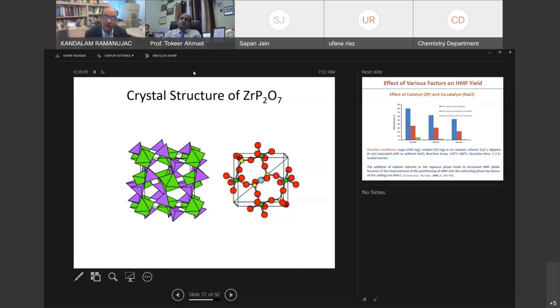But the beauty of it is, because I have a diphosphate here, there's a lot of open space you can see here. So there's a lot of chemistry that is possible. What we try to do is, zirconium is tetravalent, so we replace one of the zirconiums with two ions. One is yttrium, which is 3+. The other is lithium, which is 1+. So 3+, 1+, charge compensation is done. And the additional lithium has a space in the structure because this is a very open structure.